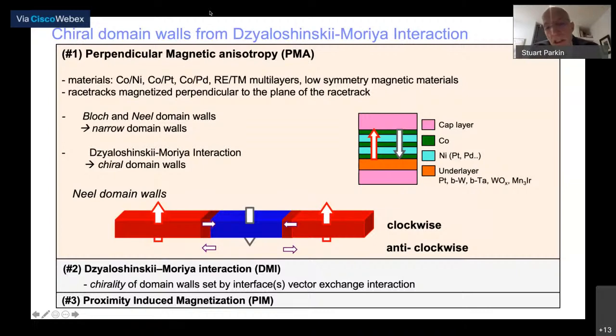And at the same time, we build these structures on underlayers that are formed from heavy metals like platinum or tungsten that have very strong spin-orbit coupling. What that does is, first, it breaks the symmetry of the cobalt-nickel multilayer, and it forces the domain walls to be chiral. They have a chirality. And this is shown in the cartoon, where you can see a red and a blue plane. And as the magnetization rotates from an up direction to a down direction, it rotates in a plane perpendicular to the domain wall and in a certain chiral direction because of something called the Dzyaloshinskii-Moriya interaction. And this is an interface exchange wherein if you break time reversal symmetry, this can lead to a vector exchange interaction between the magnetic moments at the interface.